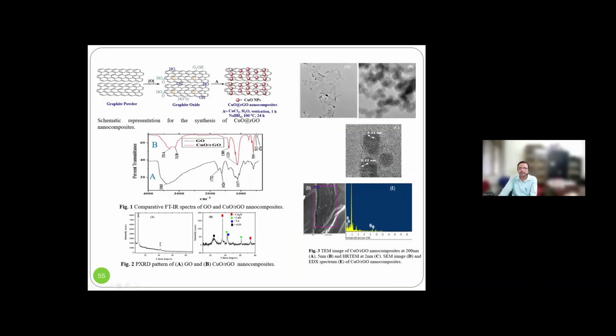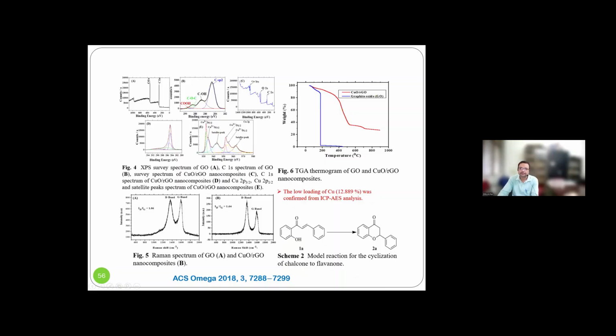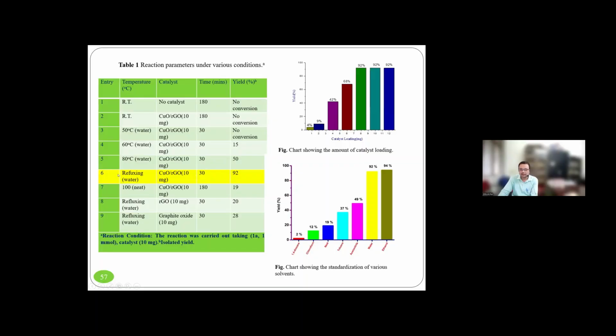Then we synthesized graphite powder to graphite oxide. Then we doped copper oxide. There, all the characterization, I will not go into the details. Then we utilized this chalcone for intramolecular cyclization. It gives flavanone. So this is the model. This is the standard protocol. Refluxing in water, copper RGO 10 mg, 30 minutes and 90% yield.